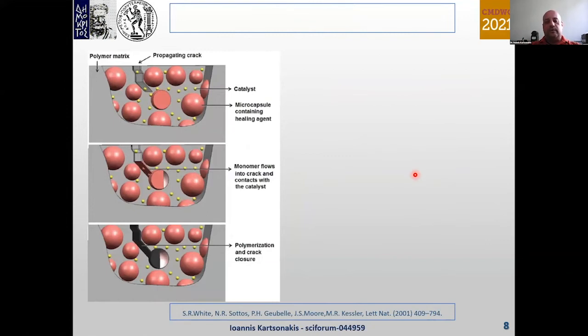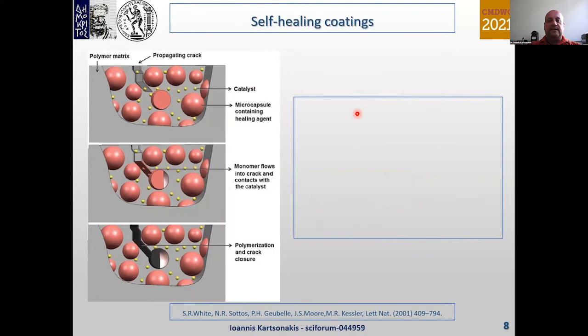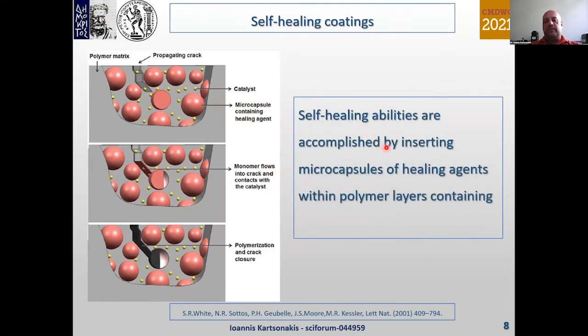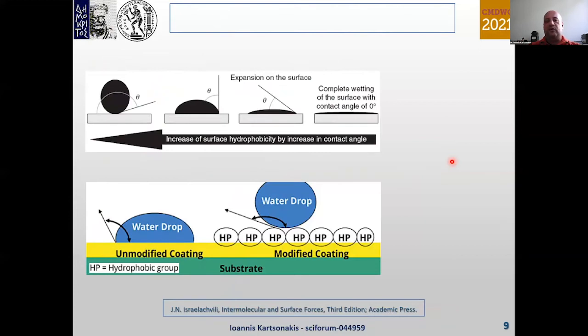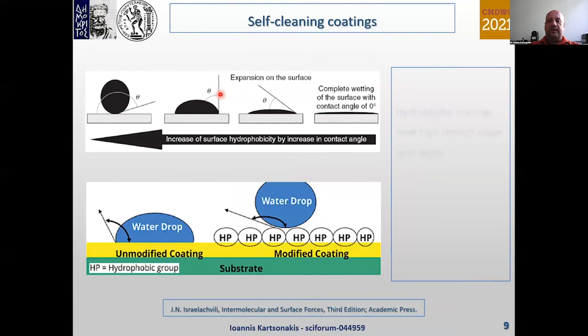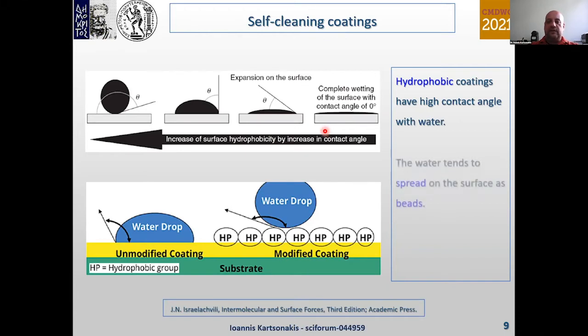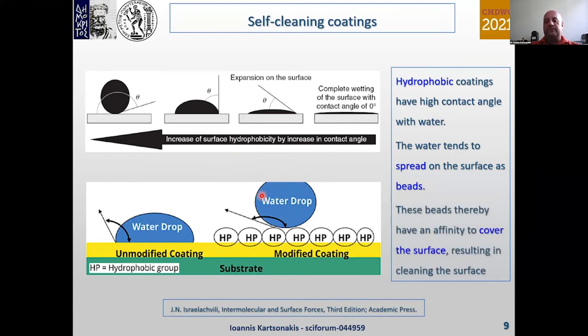This is an example from the work of White in 2001, an example of autonomous self-healing coatings. We can see that self-healing abilities are accomplished by inserting microcapsules that have been loaded with healing agents within polymer layers containing also dispersed catalytic materials. Regarding the self-cleaning coatings, we can see here that hydrophobic coatings have a high contact angle with water. We can see here from the right to the left, as the surface hydrophobicity is increased, there is also an increase in the contact angle. The water tends to spread on the surface as beads, and therefore these beads have an affinity to cover the surface, resulting in cleaning the surface.